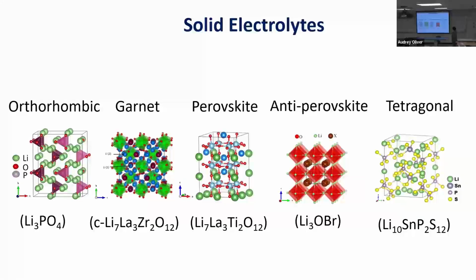These are the structures, and then we understand the ion conduction mechanism, how the lithium moves. In this example, lithium goes across this, so this is the ion conduction channel. In this case, there are two lithium sites. One is mobile, another is not, and it has a 3D channel. It's complicated. In this case, here is lithium, there is a vacancy. So the lithium goes to this vacancy site, and then another lithium goes to the other. That means the vacancy moves, so it's a vacancy migration. In another case, the lithium moves like this, goes to here, and creates a kind of dumbbell, like a lithium dimer. So it's completely different. Based on the structure, first we find out the conduction mechanism, the diffusion